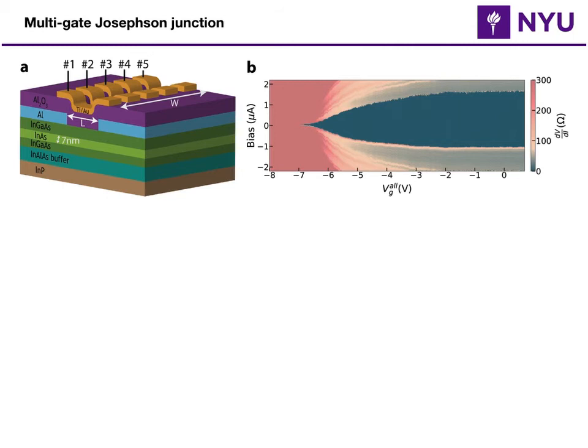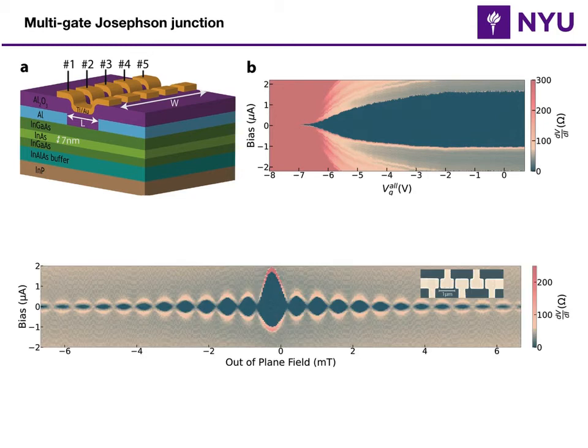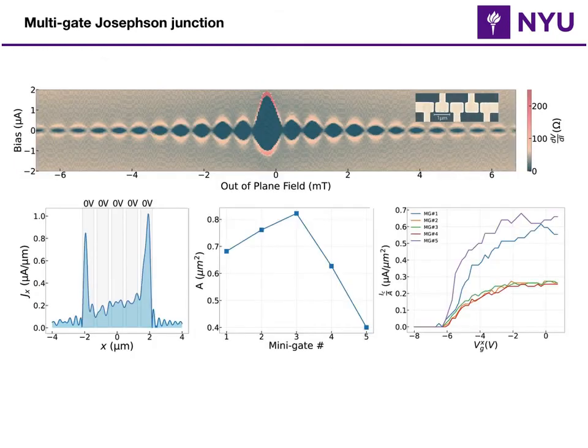I can park them back at 0 gate voltage and look at the Fraunhofer pattern, right? This is a nice Fraunhofer pattern. On the y-axis we have the current bias, and on the x-axis we have the out-of-plane magnetic field. We see many oscillations, which is nice. The Fraunhofer pattern gives us information about the uniformity of the current density in the junction. If I do an inverse Fourier transform of this signal, I should be able to get that current distribution. There is a finite size issue, but if we have many oscillations, we should get a qualitative picture. So if I do that current reconstruction, I can derive Jx as a function of x.